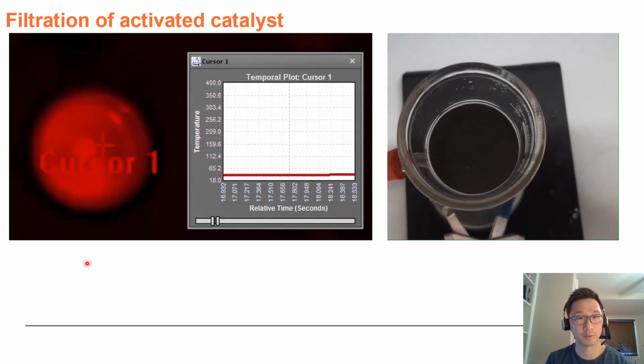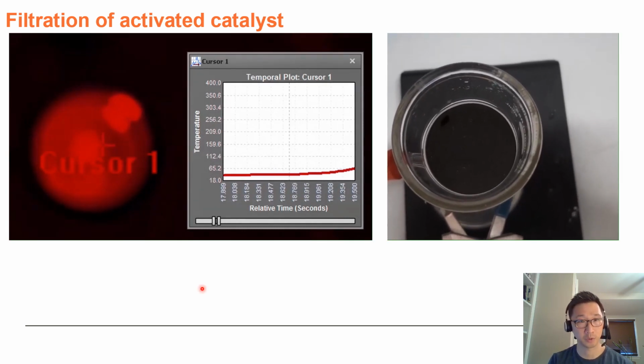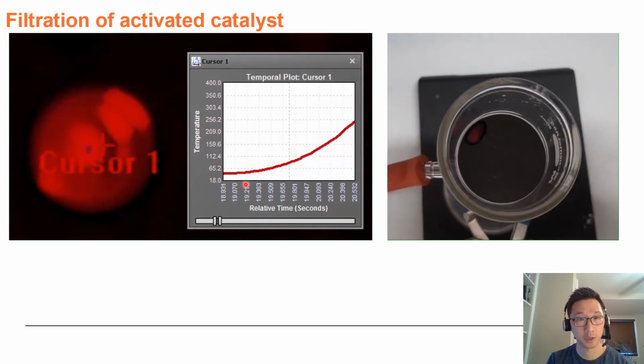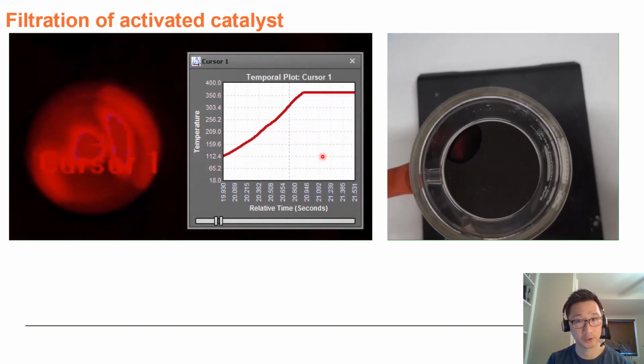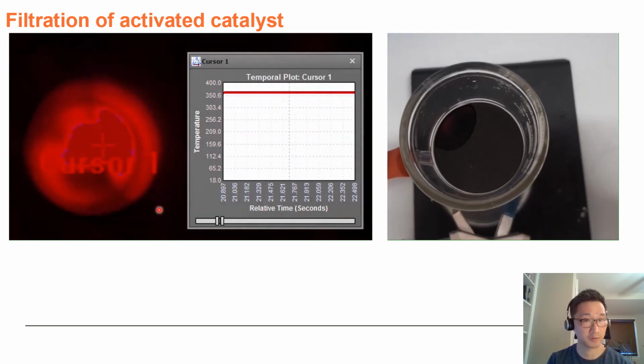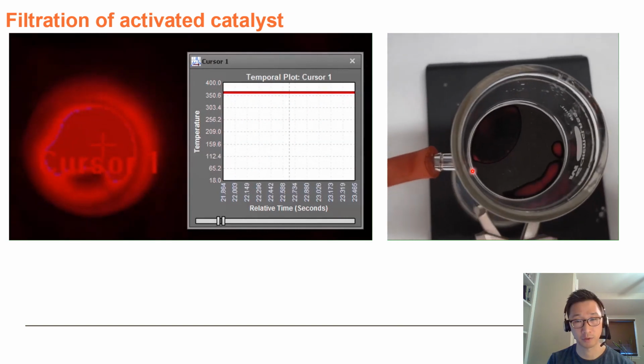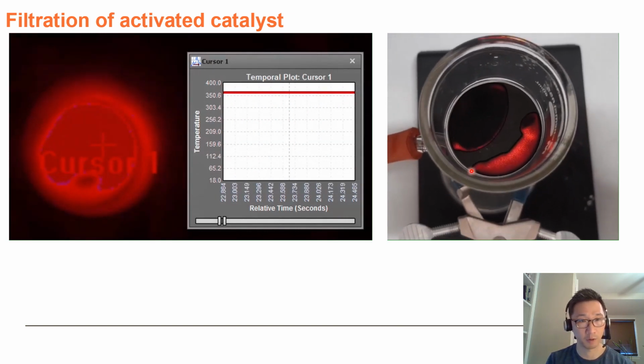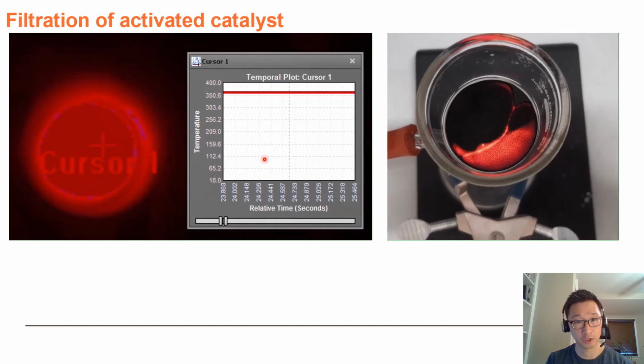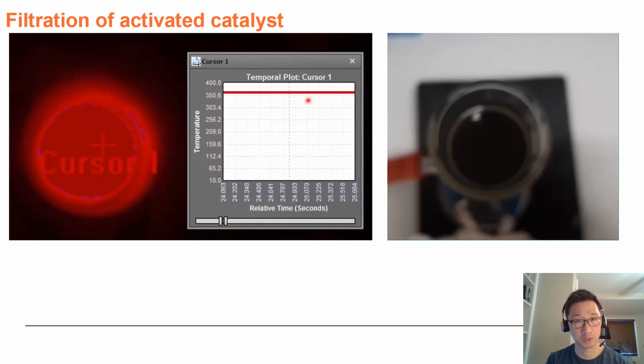So this is what happens when Raney cobalt gets dry. What I'm doing here is something you should never do, and filter the catalyst to dryness. The image on the left is taken with a thermal imaging camera, the image on the right with a standard video camera. And as you can see, upon reaching dryness, the catalyst bed reaches temperatures in excess of 350 degrees, which is the detection limit of the camera, and thus the actual temperature is probably much greater than that.